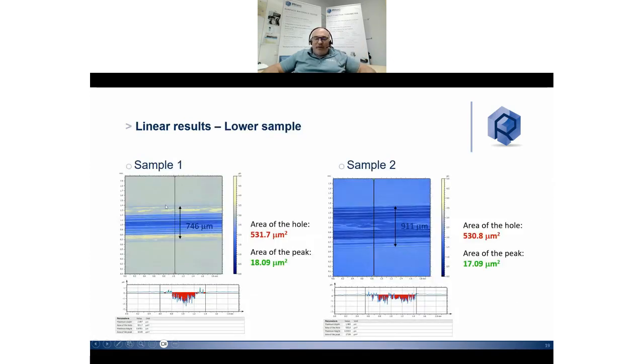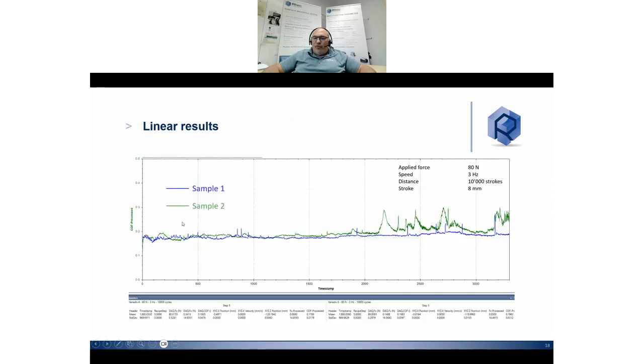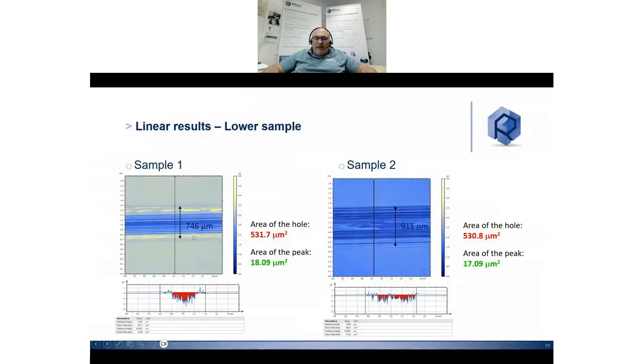Again, after the end of the test, we just scan the surface. We can compare. You see here the two materials have the same trend, except maybe at the end, the green one, sample 2, has more friction. But when you compare the wear scar at the end of the test, you see here we damage completely much more in terms of depth the sample 1, but much wider the sample 2, simply because it's harder and we break much more, we wear much more the ball during the test.